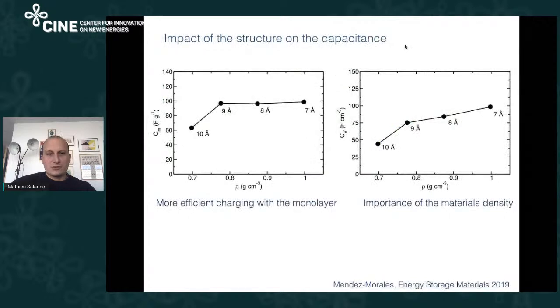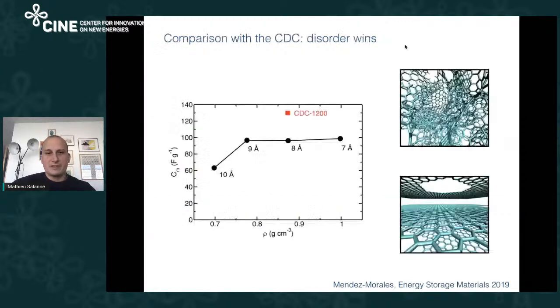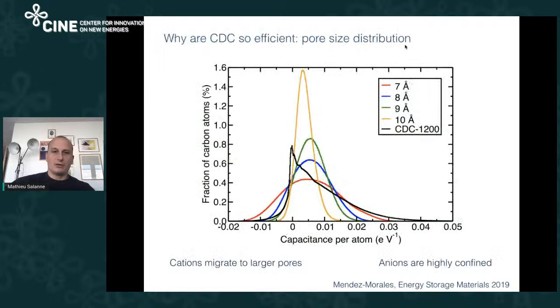But then, we have better performance with small pores, but how does it compare to disordered carbon? It's a bit disappointing because you see that the nanoporous carbon I was showing before has quite a larger capacitance, 130 farads per gram compared to 100. So it means that the disorder and the shape of the pore is also playing an important role on the capacitance. To go further into this, we again looked at the distribution of charge inside our carbon.